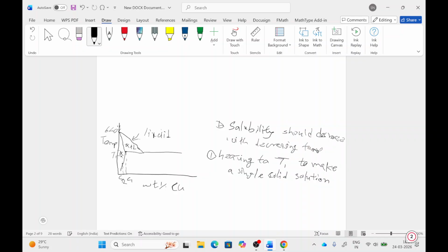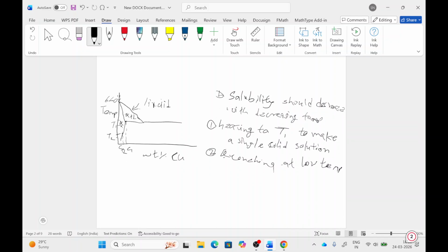So first is the heating, second we quench the sample to room temperature or a lower temperature, let's say T2. Quenching at low temperature. When we quench this alloy, all the copper will remain in the aluminum matrix, since quenching is rapid cooling.